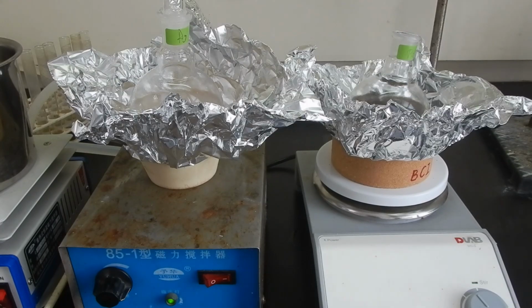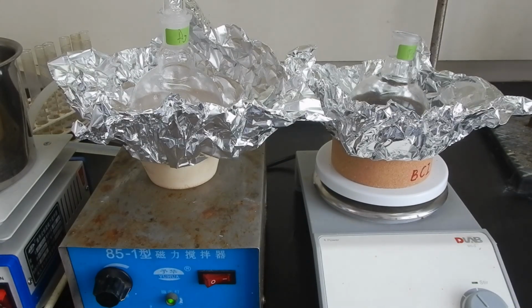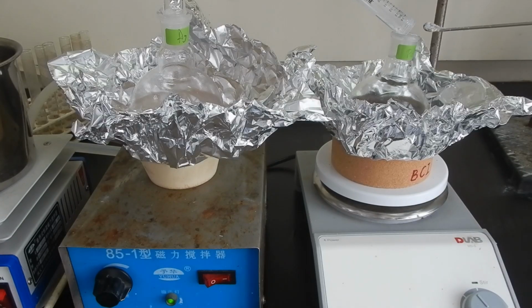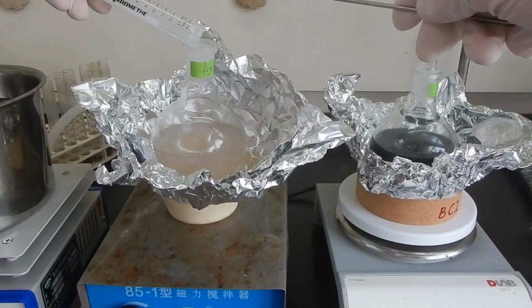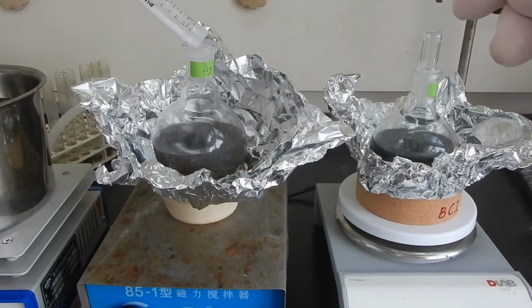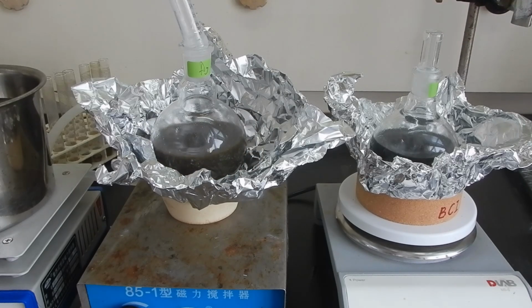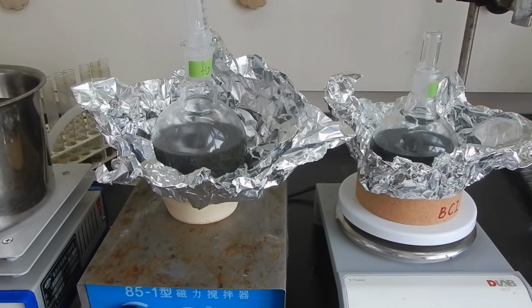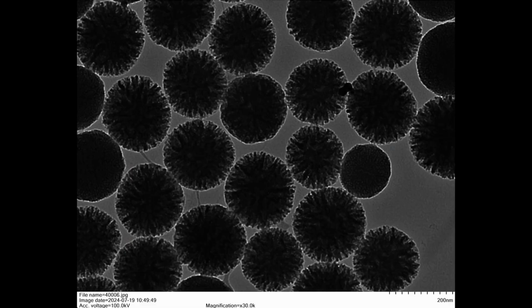After again dispersing my DMSNs in ethanol, I dissolved some silver nitrate in it and stirred the mixture in the dark for 2 hours for even mixing. Then some sodium borohydride is added, which immediately reduces silver nitrate to silver metal that deposits on the surface of DMSNs. The old trick of centrifugation, washing, and drying is repeated, and here we have some DMSN-Ag catalyst.